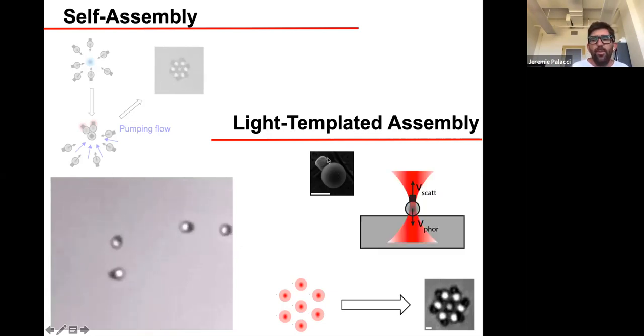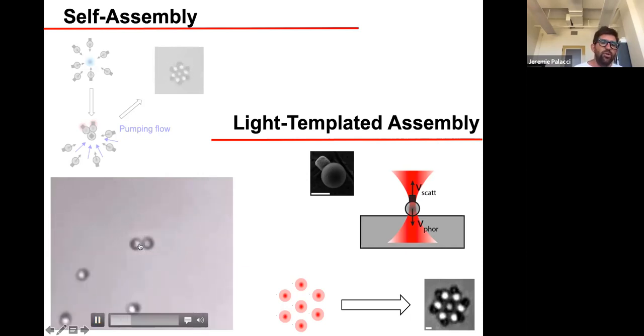So if you take those particles and try to trap them, you cannot trap them because hematite is scattering red light. And so in the absence of hydrogen peroxide, you cannot trap those particles by conventional optical trapping. On the other hand, now if you put hydrogen peroxide, those particles will be oriented by the optical trap. And so the scattering will orient them and the swimming will make them swim downwards. And so we can trap active particles using light patterns, with a combination of activity and optical trapping that we would not be able to do in the absence of activity.